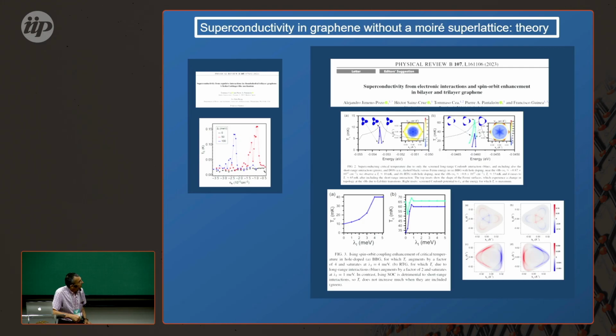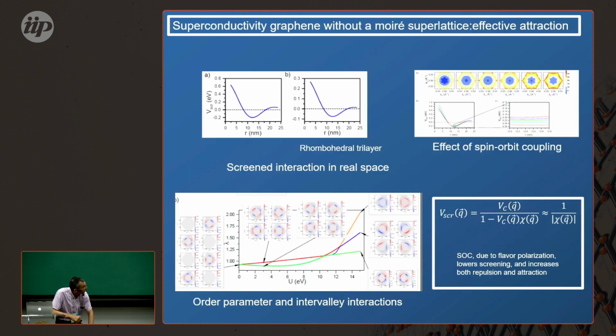As I said, the critical temperature was one or more than one order of magnitude lower than the critical temperature we found in twisted bilayer. Here the response function is not as complicated as in a twisted bilayer, because there's no moiré—it's a smooth function.